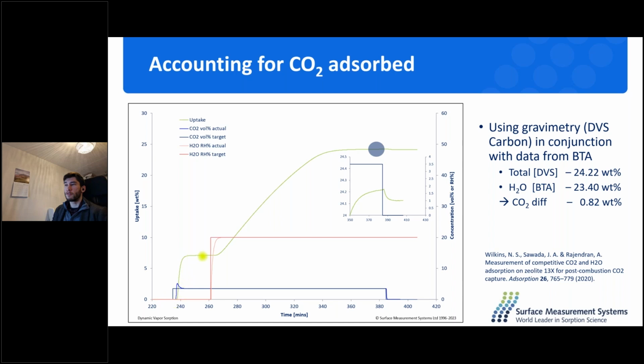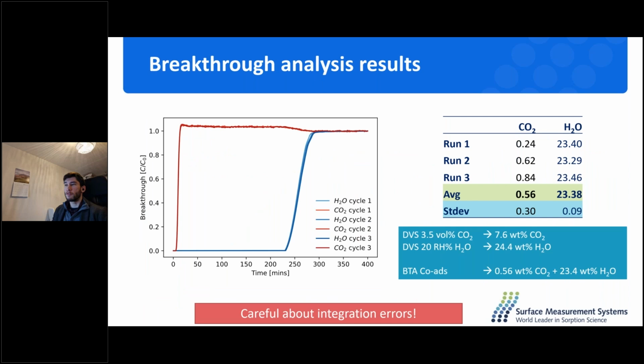So this is an experiment in the DVS carbon where we have the same zeolite 13X. There is a dose with CO2, so it's 3.5%, and then water is introduced, and then this is the total in the same conditions as in the breakthrough analysis. Here at the end, we also see that if we switch to CO2, there is some mass loss, but the point that we're interested in is this one. This is the same point, excuse me, as here in the breakthrough analysis, where there is 20% RH and 3.5% CO2.